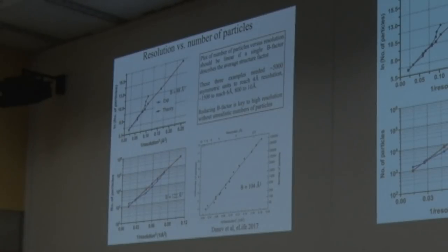And then these are two more data sets that Vinoth Kumar, collaborating with two groups in India, and he still works on these, got similar data. This was with a phase plate, without a phase plate, but similar B factors, about 100. So the idea is that this type of plot tells you how well you're doing and tries to focus you on what to do next to try and make it better. But in these three examples, at lowish resolution, say 6 or 10 angstroms, you only need about 1,000. And it's the B factor being too high that means you need more particles than we want one day to have to reach high resolution.